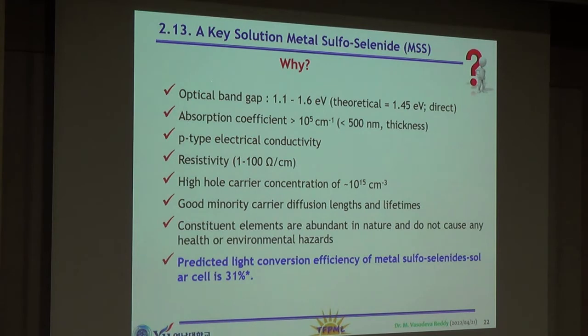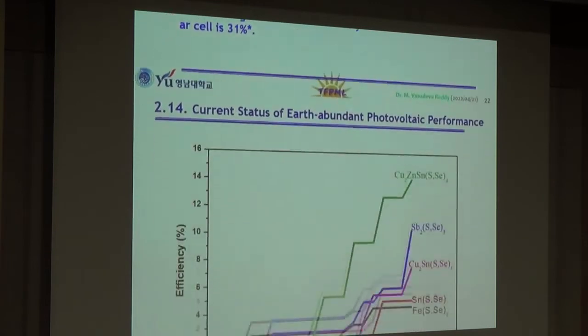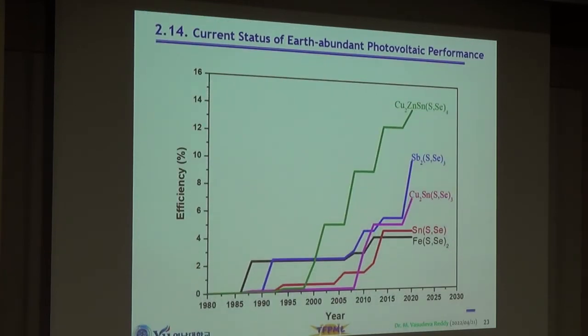So the properties of these 2 materials: the band gap of the either antimony or tin related chalcogenides is 1 to 1.5, and this has high absorption coefficient, and this material shows the p-type conductivity and resistivity is in the range of 100 ohms, and the hole carrier concentration and diffusion length is reasonable, and constituent elements are abundant in nature and do not cause us any problem, and the efficiency of these materials is higher. Therefore, we can work on tin or antimony related materials. This is the current state of the existing earth abundant material efficiency state. If you see here, tin sulfide or antimony sulfide related materials show the reasonably good efficiency.